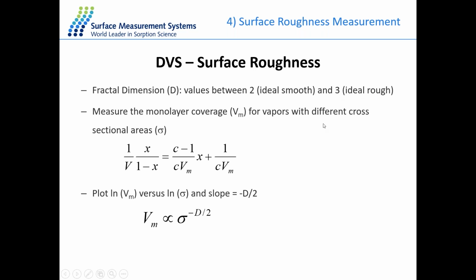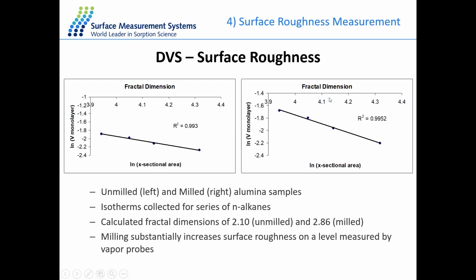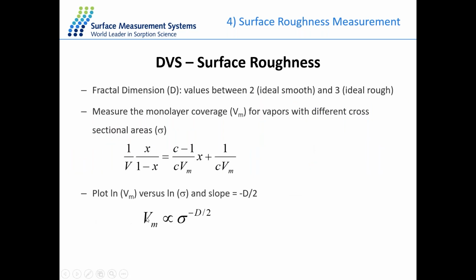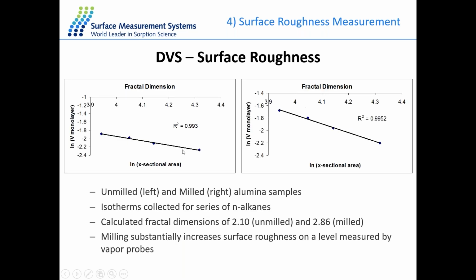And DVS here was used to measure the surface roughness of two different samples, the unmilled alumina sample and the milled alumina sample. And we use the monolayer coverage of different alkanes from hexane to decane here. We measure the absorption isotherms, and from the isotherm, we calculate the monolayer volume and plot it against the cross-sectional area of the probe molecule, and then we can get the fractal dimension of the solid sample.